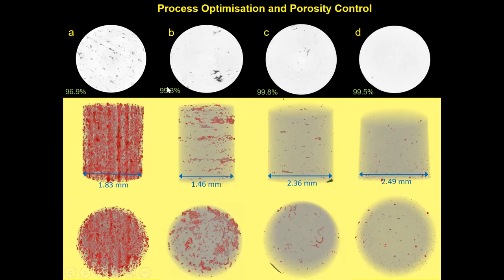Sample A has a density of 96.9%, but it includes a very high number of lack of fusion pores — these red features inside the material. It means the laser energy density applied is not high enough to completely melt the powder material and join the layers together. With changing the processing parameters, we reach a density of 99.3%, which is a high density, but still we have many lack of fusion pores inside the material.